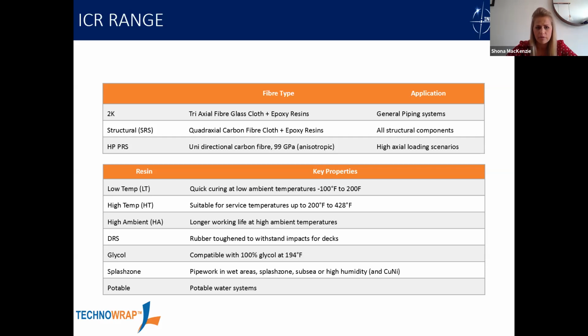We have a glycol resin, which is suitable for methanol and glycol. Then the splash zone resin, which is a hydrophobic curing resin system, which essentially displaces the water from the surface irregularities and allows that to cure either subsea or in high humidities. We also use that system for CuNi lines as well. And then finally, we have the potable water system, which, as it sounds, we would use for any drinking water or potable water tanks or pipework where you have concerns about contamination. That's a bit of an overview of the products that we have. If you can go on to the next slide.